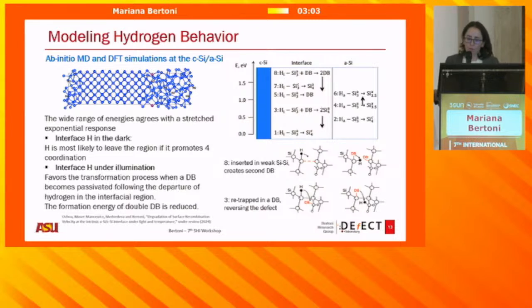When you shine light, the formation energy of this reaction that we call number 8 for some bizarre reason, and number 3, which is basically the formation of two dangling bonds and then the regeneration of one of the dangling bonds, actually drops dramatically. And so a lot of the formation of the dangling bonds at the interface really comes from the formation energy of this transformation. All of these reactions also make a very good point that it does represent what your stretched exponential is actually modeling.